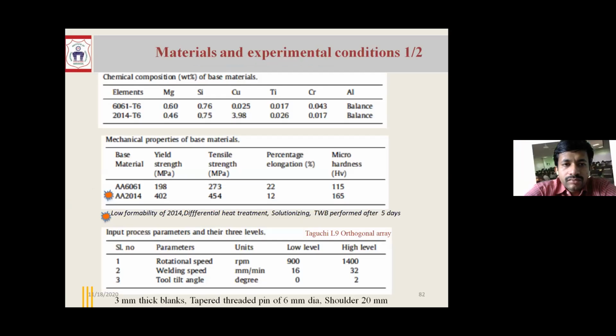So as I was mentioning, 6061 has around 22% elongation, 2014 around 12% elongation. At the same time, the hypothesis is this: you solutionize and age. I used an L9 orthogonal array. We don't want to do a large number of experiments because this heat treatment is done on a 3 mm sample. A 3 mm sample, you heat at 500 degrees centigrade and drop in water. What happens? It bends. Am I right? So when my scholar did it, he could not get a proper sample. All the samples bent, failed, and cracked.